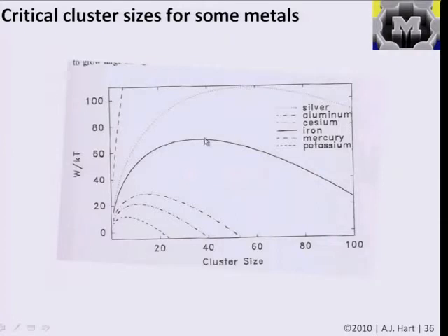So things that are substantially smaller than 1 nanometer being the sizes of vapor clusters that you'd form under particular conditions. I think this was a case where you had a background pressure of about a half torr, and you had an equilibrium vapor pressure of, say, 0.01 torr. So here, the supersaturation is about 50.